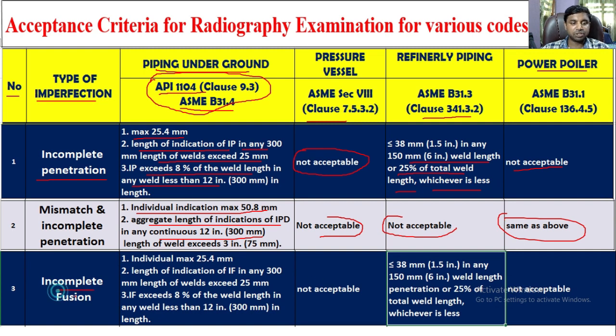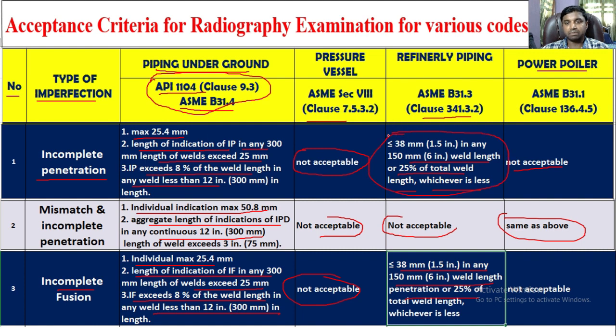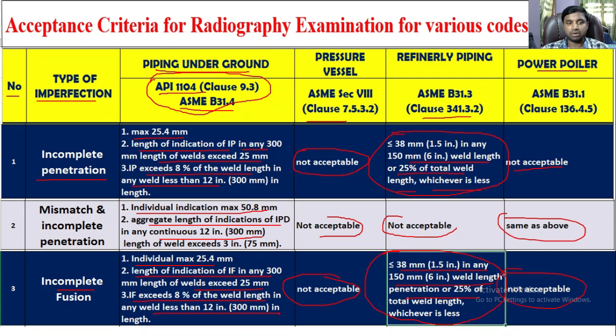Third is incomplete fusion (IF). Individual maximum 25.4 mm length of indication is acceptable for IF. Incomplete fusion in any 300 mm length: if it exceeds 25 mm, it will be rejected. If IF exceeds 8% of the total weld length in less than 12-inch (300 mm) length, it will also be rejected. Not acceptable for pressure vessel. For ASME B31.3, less than or equal to 38 mm (1.5 inch) in any 150 mm weld length applies. For power boiler (B31.1), clause 136.4.5, not acceptable.